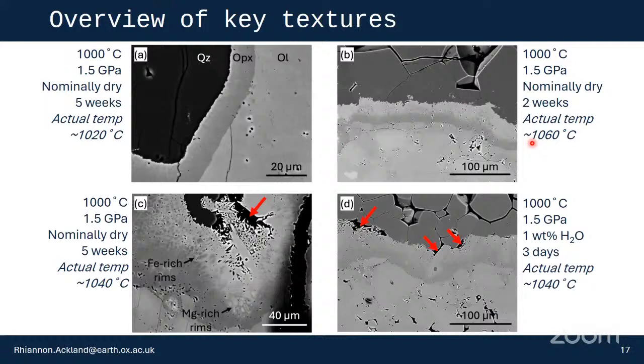And at 1,000 degrees, all of my experiments showed growth of orthopyroxene rims between olivine and quartz. And these showed a range of textures. So always the olivine-OPX interface shows these sharp, quite planar interfaces, whereas the OPX-quartz interface is much more variable. It could be also sharp and planar, like the olivine interface, or it can be jagged with the development of subhedral orthopyroxene crystals.